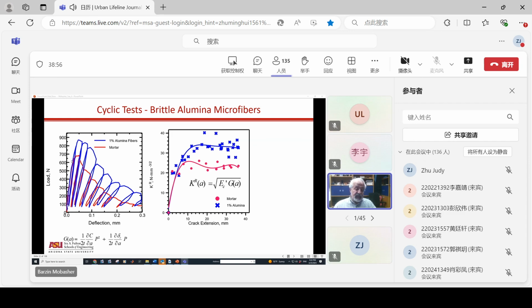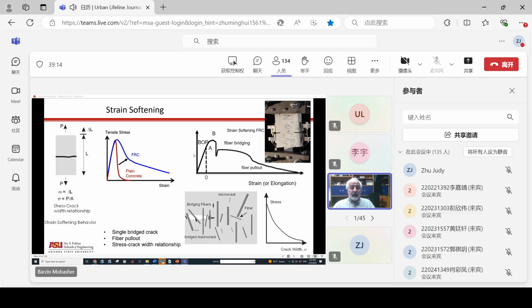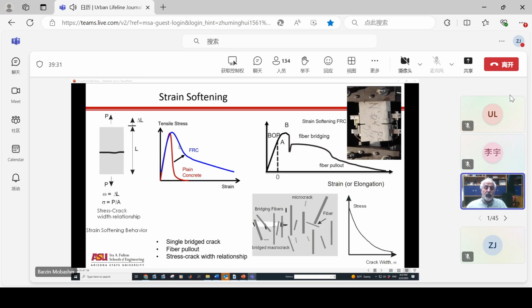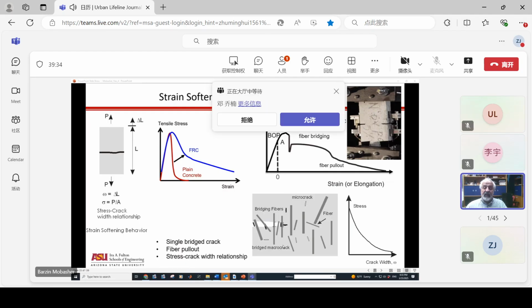So a good test for fracture measurement is this compliance calibration, where you get the R curves and you fit. And now you can say, well, I went from a level of 24 to 35 or so. And this is only using alumina microfibers. So small fibers increase the fracture toughness of the material. Now, when we do that, we get basically the process that we call strain softening. That means that once I reach the peak, I don't have a fracture problem. I don't have a big, huge sound. The FRC material basically carries more load as it's growing. And that has to do with this fiber pullout because of the bridging fibers, which I mentioned to you.